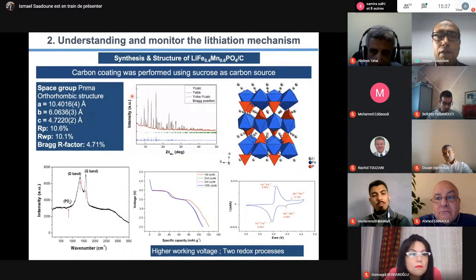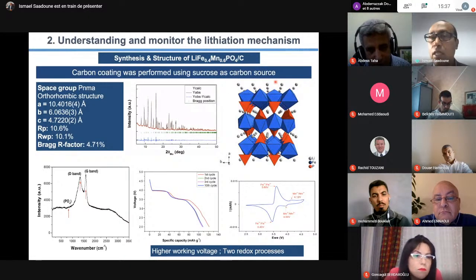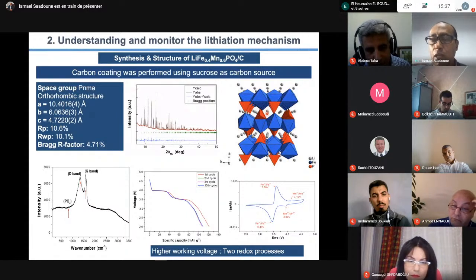So here you have XRD. This is the job of the chemist, of solid-state chemists. We start by XRD, you understand the structure. You see that we have tunnels of lithium, so we can remove and put lithium very easily and very reversibly.